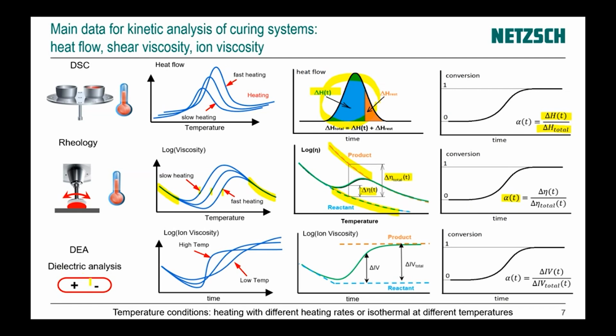Next one is dielectric analysis. In this case, we measure the ion mobility of our dipoles. Here we apply an alternating voltage and measure the current and see how our dipoles rotate with the changing of the voltage. Ion viscosity is 1 divided by ion mobility. And here again, we can see how the reaction goes on.